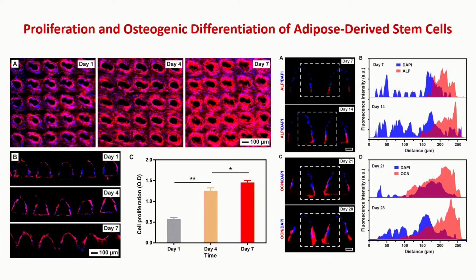And then we also look at their differentiation. In this case, we are using a different type of marker for the osteoblast. It's an alkaline phosphatase marker. So you can see the gradual change. When you move from the top to the bottom region, you are going to have a gradual increase in terms of ALP levels. So that indicates increased osteoblast formation. And this is an early marker actually for ALP. And here we are using a later marker, OCN, osteocalcin marker. In that case, you also see this similar trend. From top to bottom, you're going to have an increase in terms of osteoblast generation.